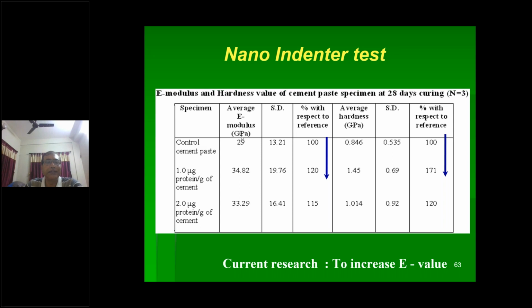Then what we are getting, that average E value is 29 in these cases. If we add the protein, it increases to 34 GPa to 33 GPa in this range. And with respect to that, your standard deviation values. So about 20% to 15% improvement in your E values. Similarly, the average hardness also increases to 1.45. It is slightly less in these cases.